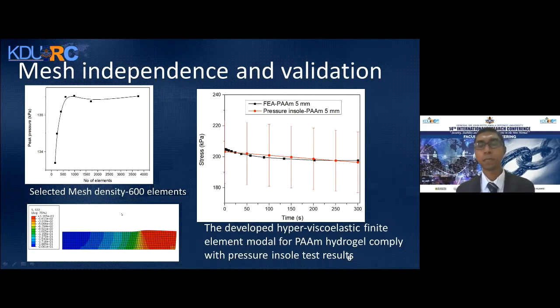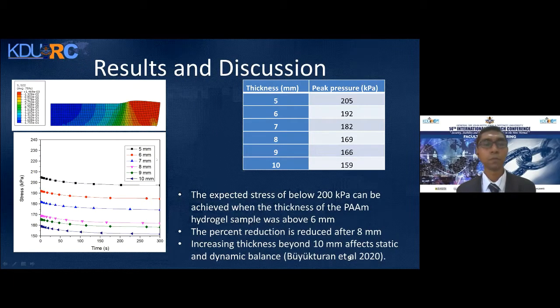So after that, we change the thickness of this model in finite element, check the values, and you can see when you increase the thickness, the peak pressure tends to decrease gradually. But our requirement, the limitation, is we have to reduce this peak pressure below 200 kilopascal. So when it is 5 mm, we can't achieve that. It's 205. So above 6 mm, the peak pressure will reduce below 200 kilopascal.